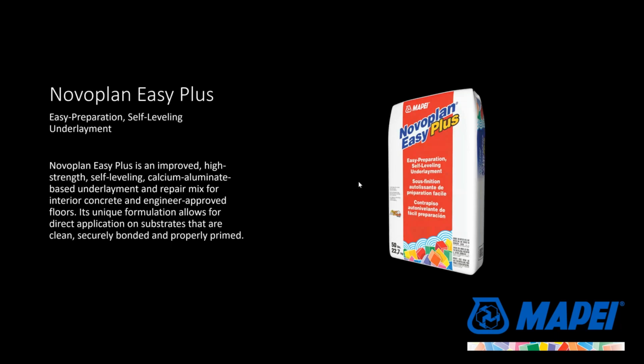Then we get into the calcium aluminate based materials. Novoplan Easy Plus has been with us for many years now. Its claim to fame is that it can be used over non-profiled concrete or other surfaces, can be used over existing well-bonded flooring, for example. This was one that we've done pretty well. This is a shrinkage compensated formulation. It's a little bit slow to dry, but it's got good compression results, and on the lower cost side of the fence when it comes to self-leveling underlayments.